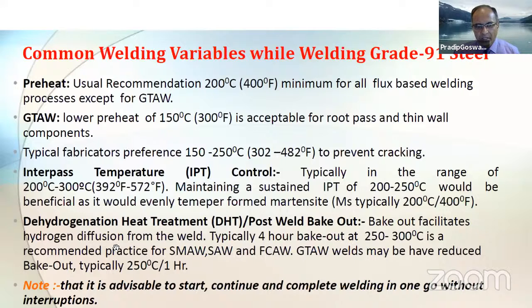The DHT basically facilitates the hydrogen diffusion from the weld. Typically, a 4-hour bakeout at 250 to 300 degrees centigrade is a recommended practice for SMAW, submerged arc, and flux core arc welding. For GTAW welding, for full TIG welds, it may be reduced to typically 250 degrees centigrade for 1 hour. That is because GTAW consumables typically have very little or almost zero hydrogen in the weld deposit.